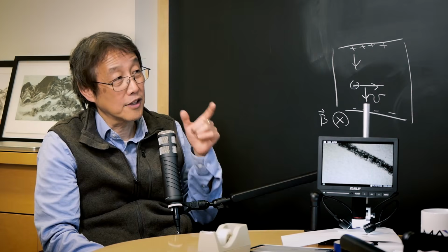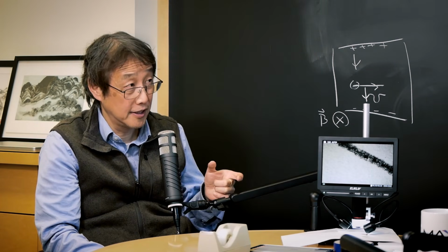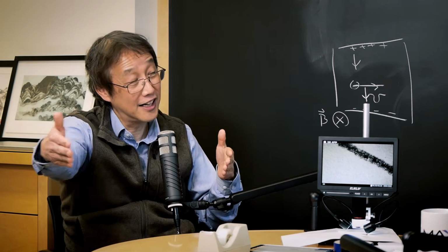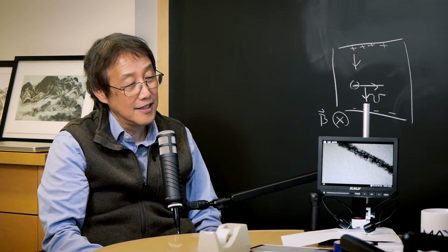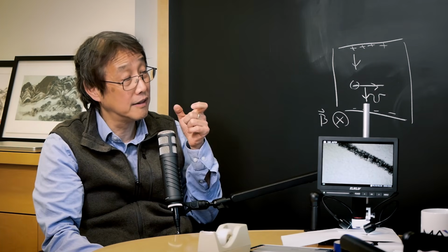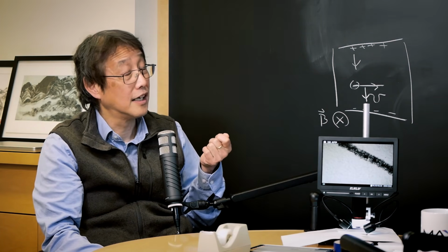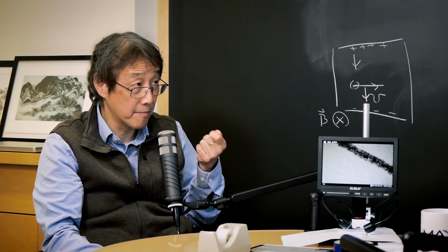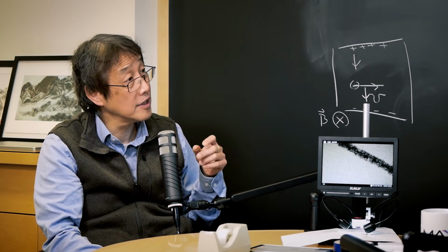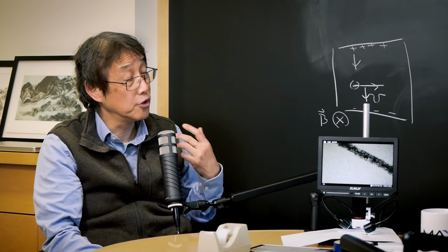And you see that once your sample is separated out on the silicon wafer, you can make the device, because that's the way that we make devices on nanotubes, right? Yes. So from there on, we know what the technologies are. So we made the device. And because this one is not sonicated, and you're starting from high quality graphite rather than graphite powder, in some sense the quality of the sample is good enough. So once you do the transport measurement, you can see strong gate dependence, very strong Shubnikov oscillation, a semi-classical quantum oscillation, which is tuned by the gate voltage. All these things were very exciting results.